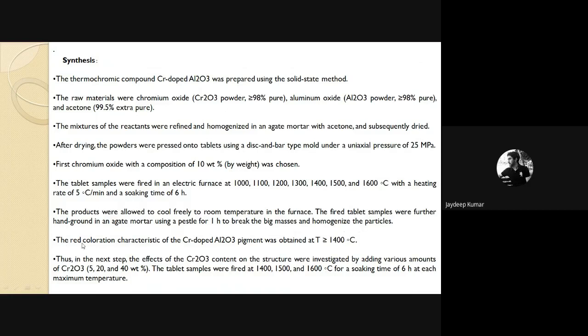Then the red coloration was observed, the typical red coloration which is the property of chromium doped Al2O3 ruby, at temperature more than 1400 degrees centigrade. So this was just experimental, to observe when it is going to give its property color. Till here it was observed that it was just green, and it started having its pink or red color from 1400 to 1600 degrees centigrade, so above 1400 degrees centigrade.